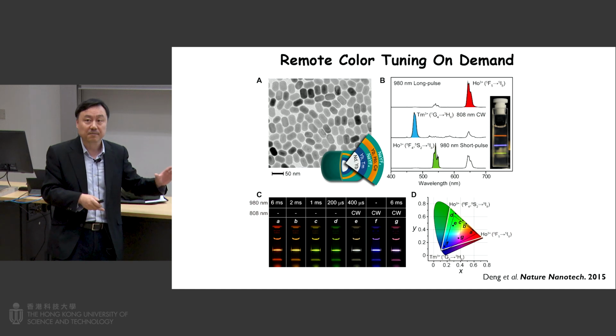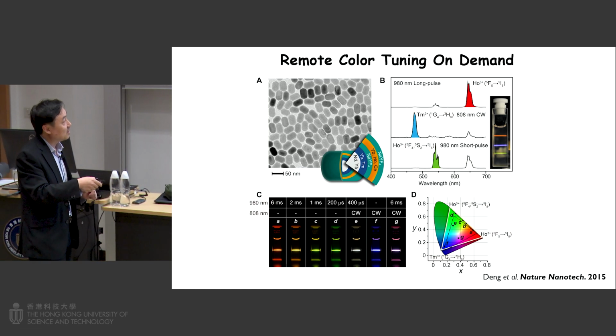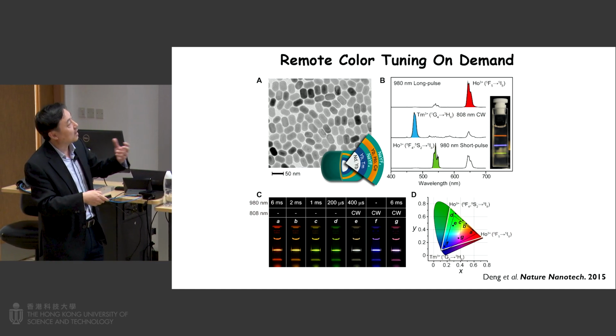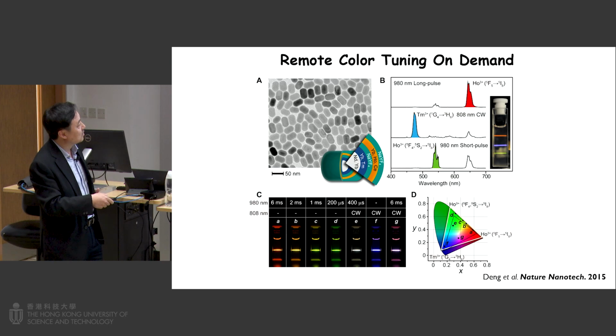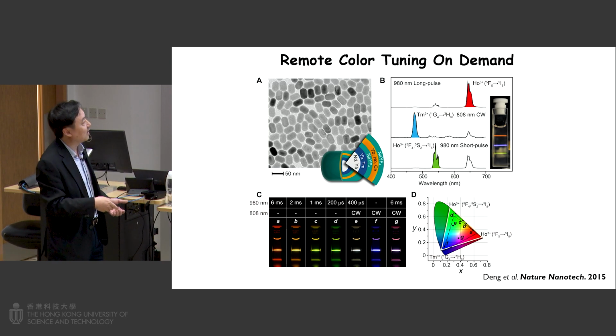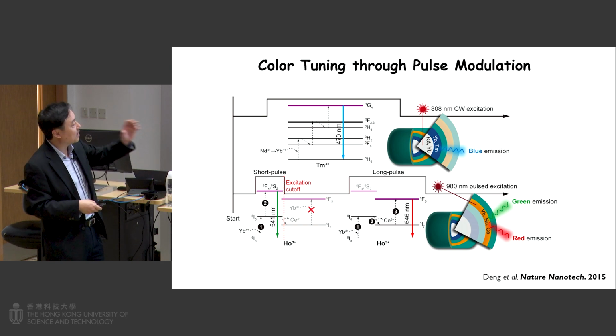So this is quite amazing. It turns out that we can actually use this core-shell structure to control the energy transfer rate between different lanthanide ions. So we can even achieve multi-color tuning, even achieve white color using these designs. So that's the mechanism here.